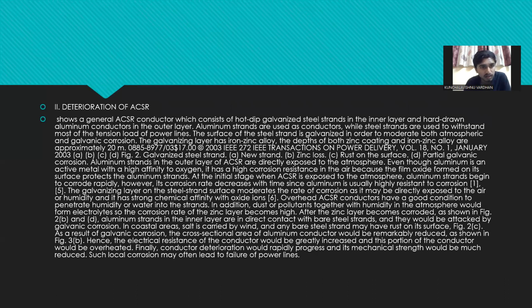Deterioration of ACSR. A general ACSR conductor consists of hot dip galvanized steel strands in the inner layer and hard drawn aluminum conductor in the outer layer. Aluminum strands are used as conductors while steel strands are used to withstand most of the tension loads of the power line. The surface of the steel strand is galvanized in order to moderate both atmospheric and galvanic corrosion. The galvanizing layer has iron zinc alloy. The depths of both zinc coating and iron zinc alloys are approximately 20 micrometers.